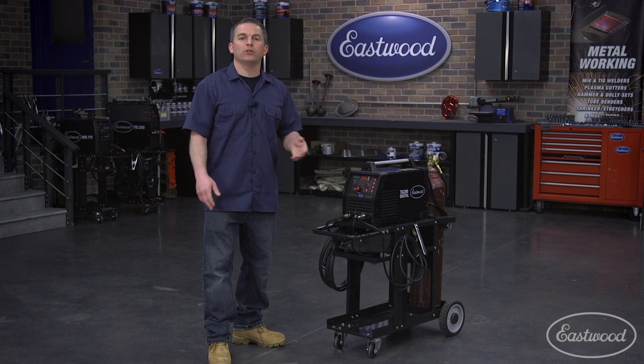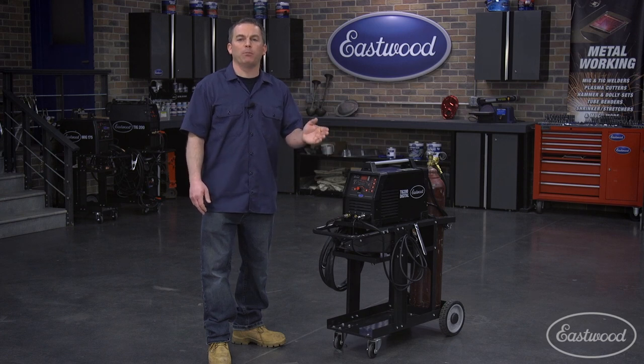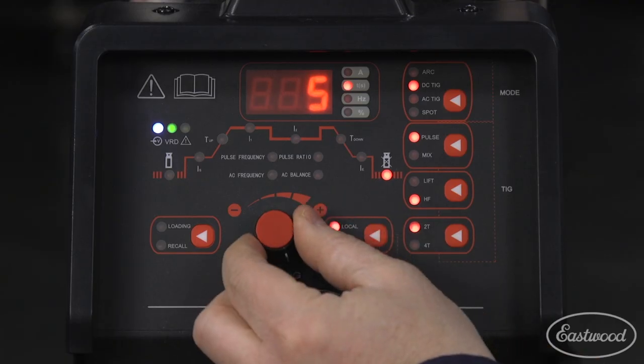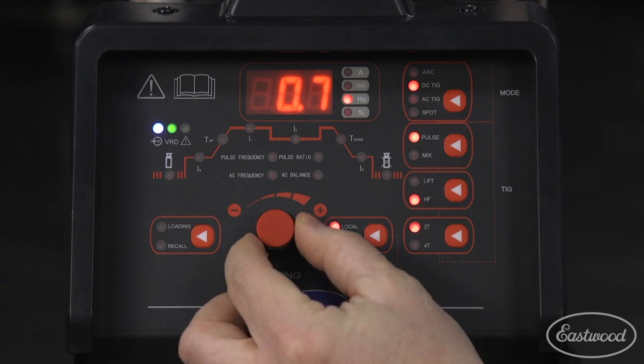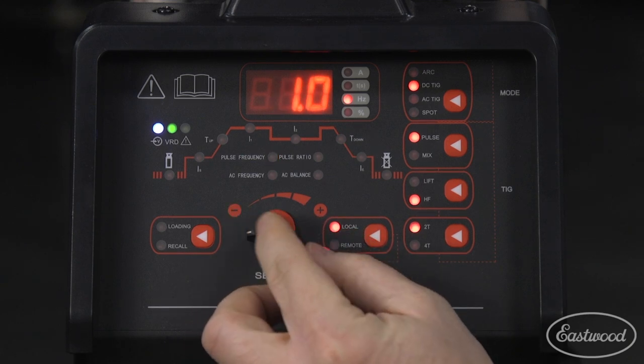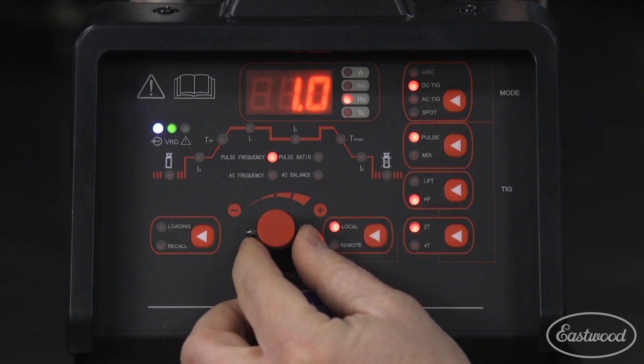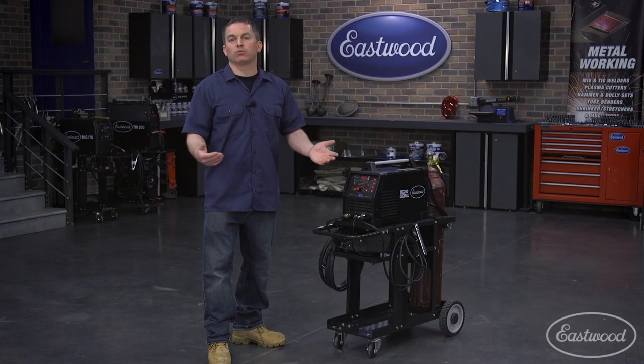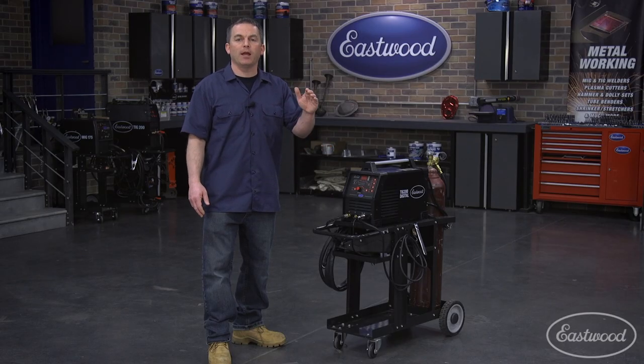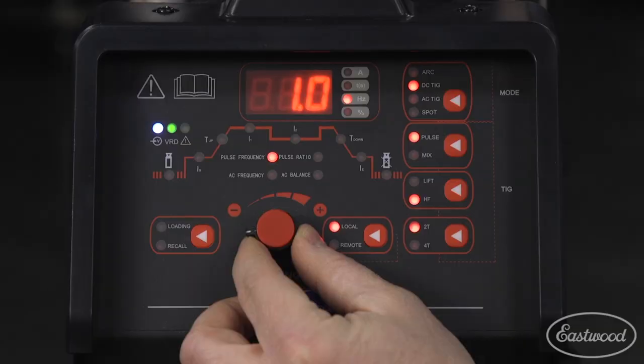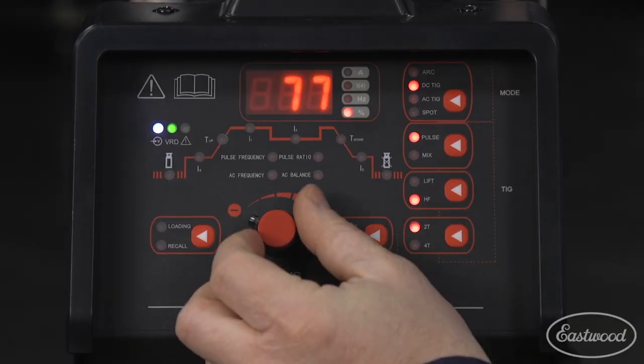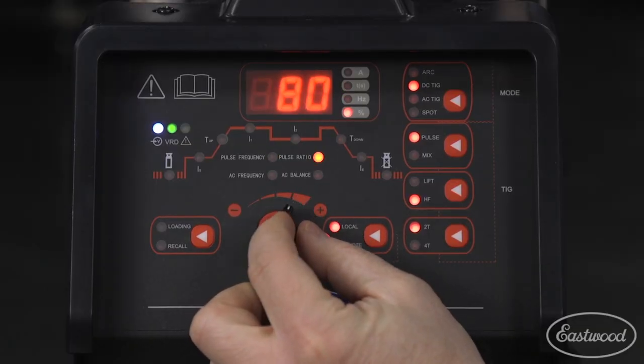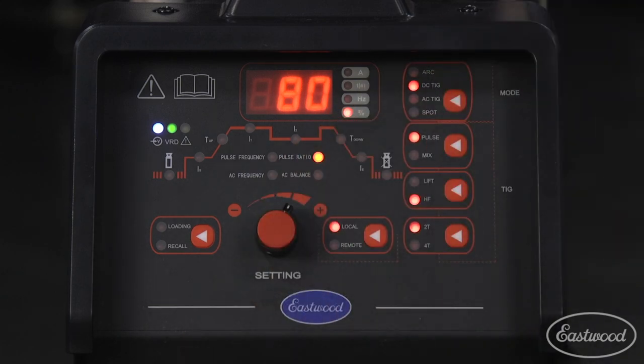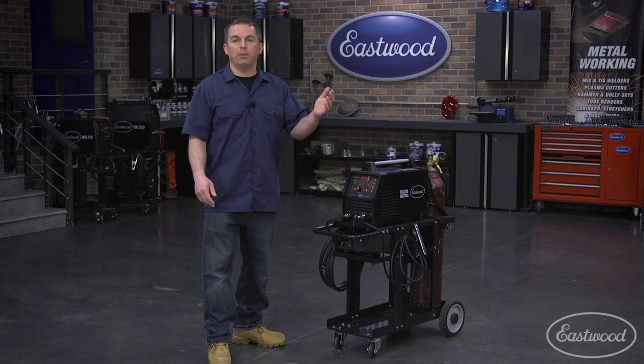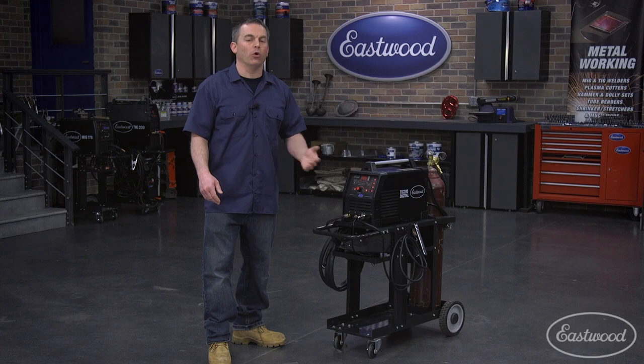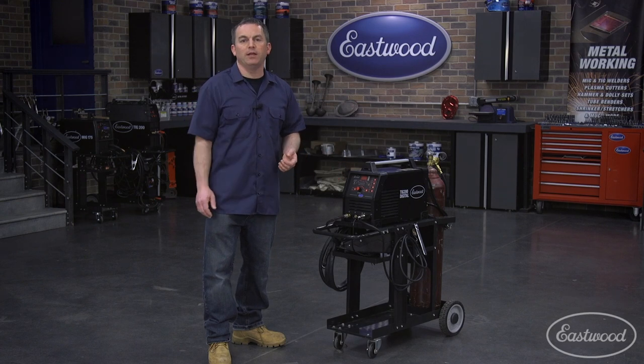With DC pulse, you'll now set the pulse frequency and pulse ratio. The pulse frequency is how often per second this pattern happens. So if you set it to 1, this pattern will occur 1 time per second. Pulse ratio is the ratio of the peak amperage to the minimum amperage. So if you set it at 80%, it will be at the peak 80% of the time and the lower amperage 20%, or 8/10 of a second on peak, then 2/10 of a second on the lower amperage, and then it will repeat the cycle.